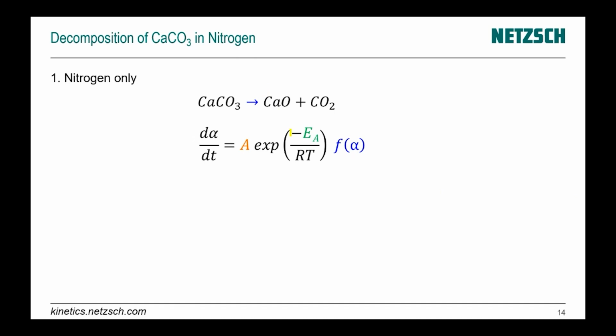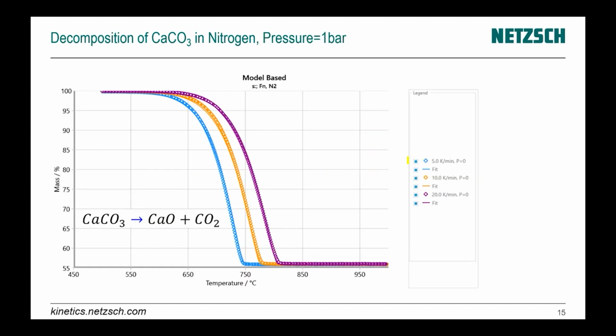And here is our equation: forward reaction and backward reaction, and we have a total reaction rate. Now with our calcium carbonate, if we have only nitrogen, then there is no backward reaction because we have no presence of carbon dioxide. We have only forward reaction, and here is our kinetics. We will make a measurement with pure nitrogen with 5, 10, and 20 K per minute. And in Kinetics Neo software, we can create the model which depends on temperature only. And now let's add the dependence on the pressure.